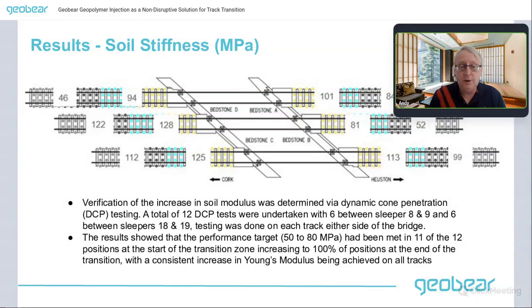A total of 12 DCP tests were undertaken, with 6 between sleepers 8 and 9, and 6 between sleepers 18 and 19 on the general track. Testing was done on each side of the bridge. The results show that the performance target of 50 to 80 MPa had been met in 11 of the 12 positions at the start of the transition zone, increasing to 100% of positions at the end of the transition, with a generally consistent increase in Young's modulus achieved on all tracks.